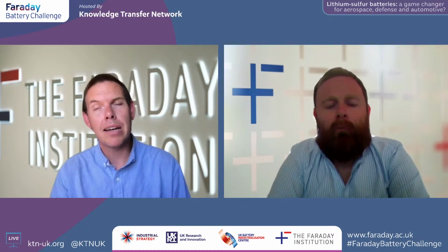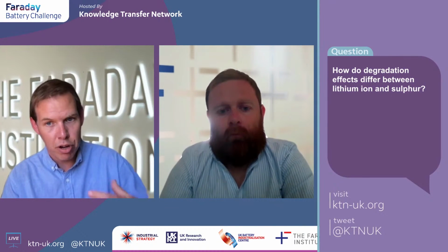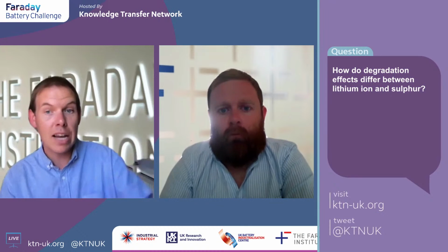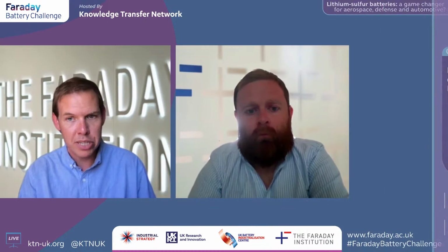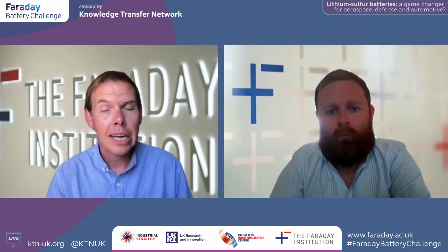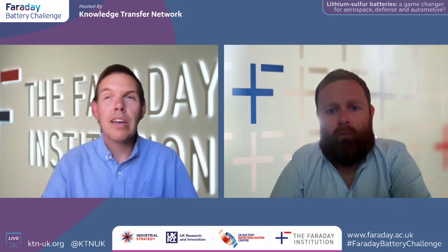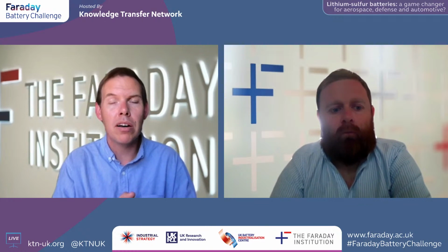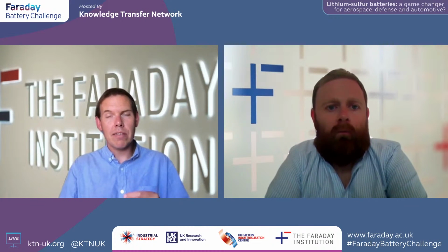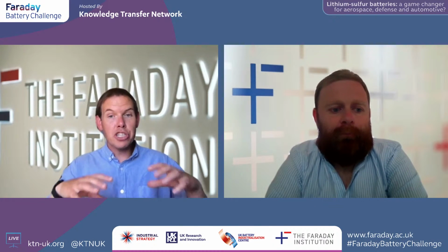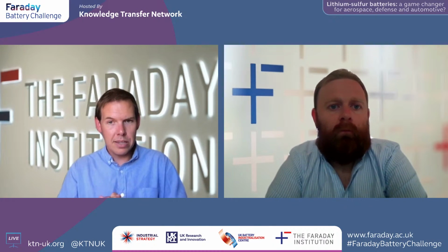Got a question: how do degradation effects differ between lithium-ion and lithium-sulfur? Do they degrade in the same way? I mean, the short answer is no. They don't degrade in the same way. We're using very different electrodes in the lithium-sulfur system, and because of that phase transition from solid electrodes to sort of liquid active materials during the charge and discharge process, there are some quite different degradation processes that happen, and again, that provides us with some challenges in the fundamental understanding of that, but also, given the insight that we are gaining from our fundamental investigations of electrochemistry and material science, it provides us with some really exciting opportunities to engineer designer materials that can be much more degradation tolerant.